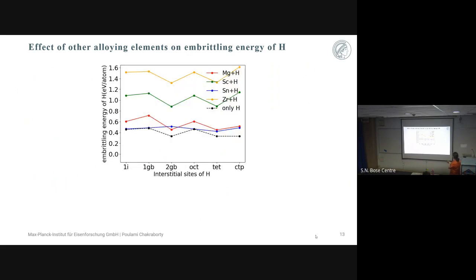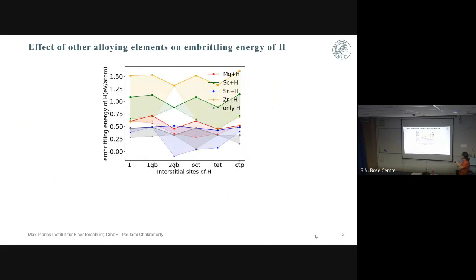Each of these points has been calculated based on the segregation energy corresponding to each of these interstitial sites. But the segregation energies are highest in one or two sites only. So realistically, where the segregation energies are mostly negative, the hydrogen will have the tendency to go there. If we consider that case, we will have this second, almost dotted line for each of the corresponding elements, which typically shows the lower limit, where hydrogen goes to the interstitial sites with the lowest segregation energy, or highest probability where hydrogen might occupy. We end up with these energy plots, which don't change the trend.